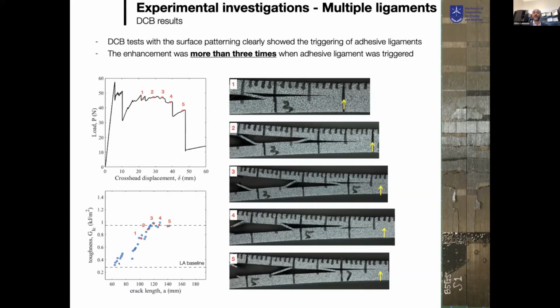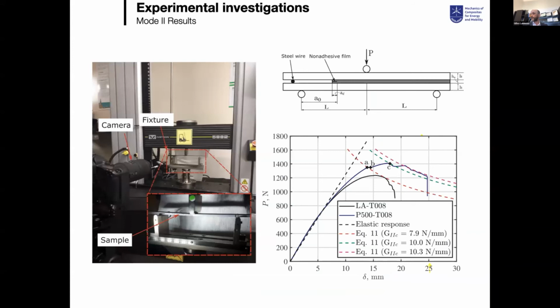That means you increase by 300, 400% the performance of your structure without changing your material. You just change the way you architecture the material. And you have really huge improvement to get from such technology. You see here the increase of the R curve between the baseline, that means what you will get without any patterning, to what you get when you are designing this pattern.